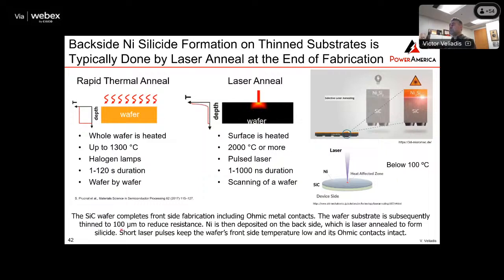So the way you make devices, a common way to make devices, is you process the device till the end, and then when you get to the end, you want to thin the substrate to reduce the resistance. You don't thin the substrate at the very beginning, because if you take the 350 micron substrate and you make it a 100 micron substrate at the very beginning, then during processing, the wafer is going to crack. That's way too thin for mechanical stability. So what you do is you process the wafer fully, and when you get to the very end, you put resist at the top of the wafer, you flip the wafer over, and that's when you go and thin the substrate. And after you thin the substrate, you're using this laser anneal to create silicide. You put nickel and do this laser anneal to create silicide at the back of the wafer, which serves as the drain.